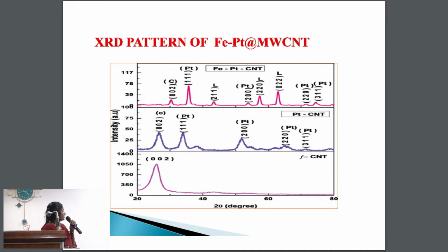Next is confirmation. The crystal structure was analyzed by XRD pattern. The first pattern, with the 002 peak, is functionalized multi-walled carbon nanotube. The second one is platinum decorated multi-walled carbon nanotube, with 111, 200, 220, 311 peaks being platinum peaks and 002 the multi-walled carbon nanotube peak. So I confirm platinum is incorporated in the carbon nanotube. The third is iron and platinum decorated multi-walled carbon nanotube. The 002 is the multi-walled carbon nanotube peak, 111, 220, 311 are platinum peaks, and 211, 220, 022 are iron peaks. So I conclude iron and platinum are successfully incorporated in the multi-walled carbon nanotube.